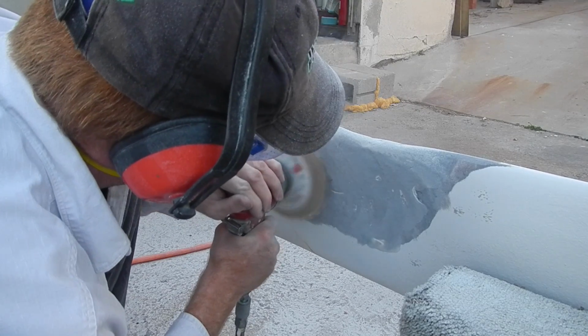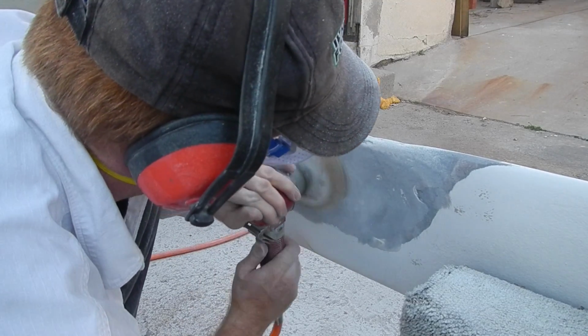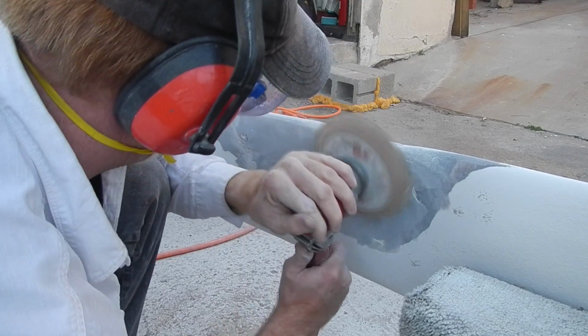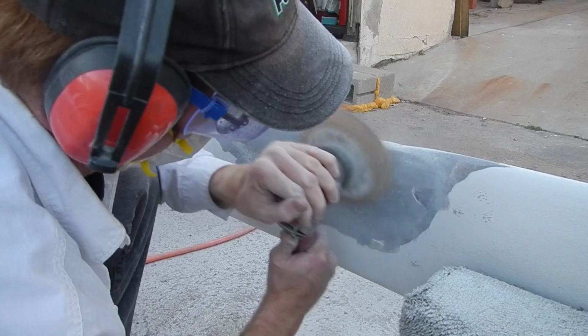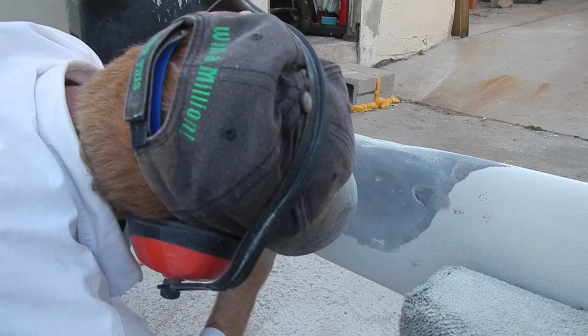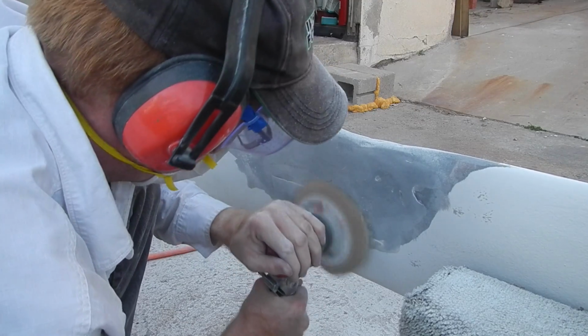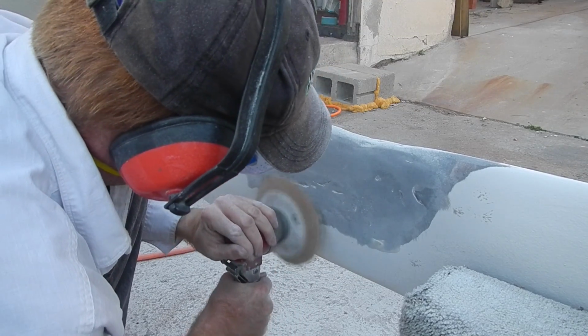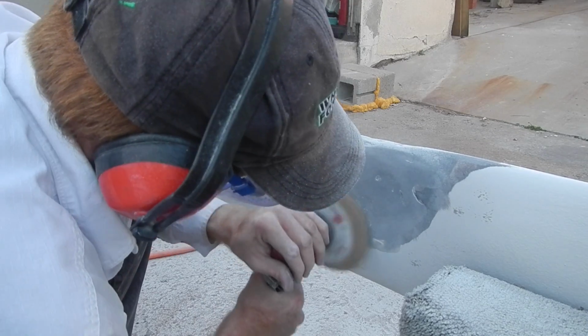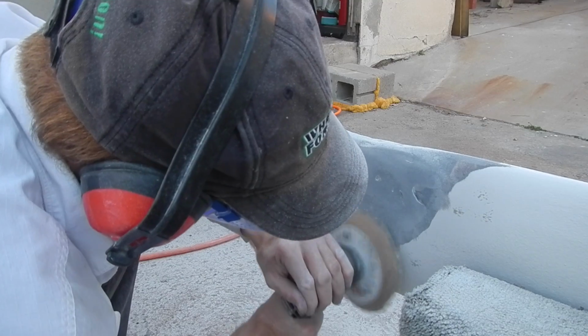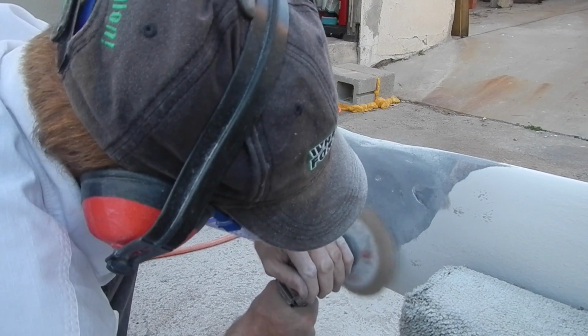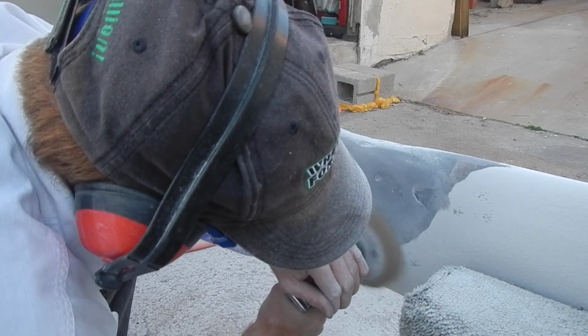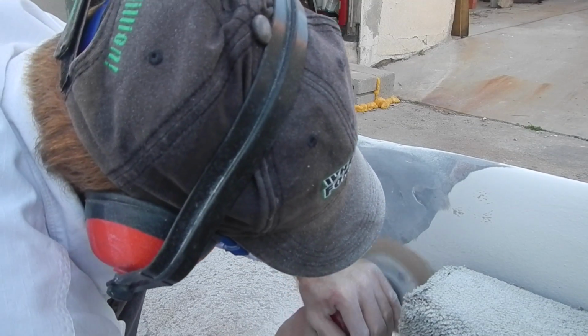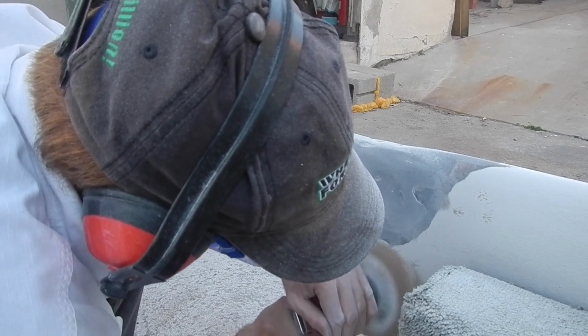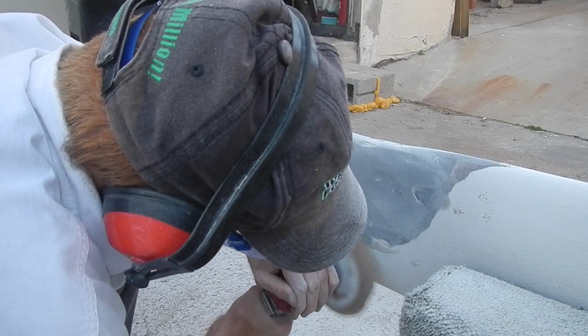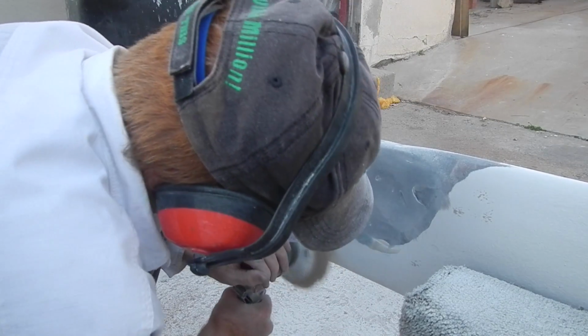Bondo is bondo. You can get it for cars, you can get it for anything, but what I was using was a fiberglass infused bondo that took the same hardener as a normal bondo, about 2 inches of the hardener, which is a red liquid substance, put on top of a big dollop from your putty knife that you use. 2 inches of that hardener will mix in and give you enough working time to get a large dollop spread out as best you can. When you start noticing that the bondo is physically moving with the putty knife and not smoothing out anymore, that's when you're done. The bondo is pretty much dry. If you continue, you're just going to cause more and more bubbles, and bubbles are bad in this situation. You want to have the least amount of bubbles, the most amount of smooth surface, so that you don't have to rebondo too much.